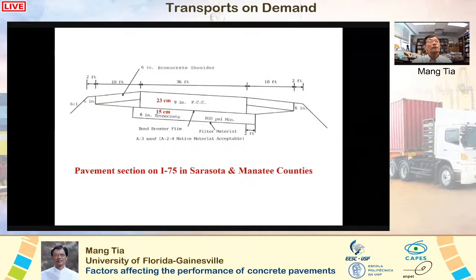Well, because of the problems they have seen on the I-10 concrete pavement, a new design was adopted for this pavement. An even stronger base was used for the concrete slab. The base used was a 15 centimeter Econocrete, as shown here in this drawing. The shoulder lane was also constructed with Econocrete, as shown here. Econocrete is concrete with relatively lower strength than normal concrete, but it's much stronger than the cement-treated subbase.